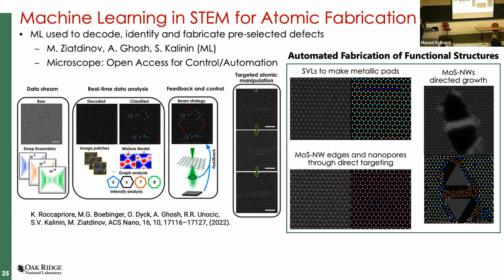In 2017, Maxim, at the time when he was a postdoc, published a really important paper. If you take a STEM data set with all these different defect populations, like vacancies that start forming, if you have graphene, you can create Stone-Wales defects, so a little bit of a departure from the 6-fold symmetry. You can take the time-resolved data set and track it over time and really understand what's going on as far as the pathways. We wanted to integrate that in the microscope.